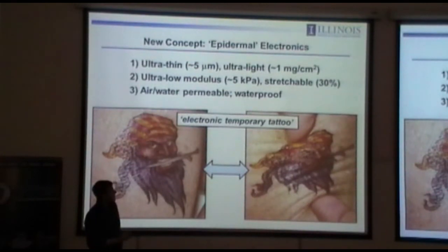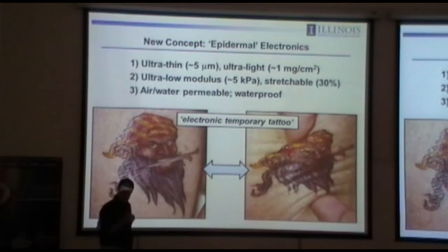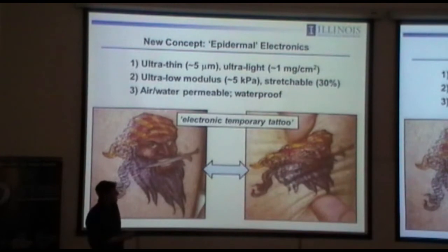So what does that really mean? That means you want the entire integrated circuit to be ultra-thin, as thin as you can go. We thought 5 microns was a good target when we started this. As light as possible, to avoid mass loading, so maybe 1 mg/cm² was a target we thought about. Ultra-low modulus, you want it to be as soft as possible. I'll tell you the physics of why that is in a second. We thought 5 kilopascals would be a good target because that happens to be the modulus of brain tissue. The skin modulus is a little bit higher than that, more like 100 kilopascals, but that was an aspirational target when we first started out.